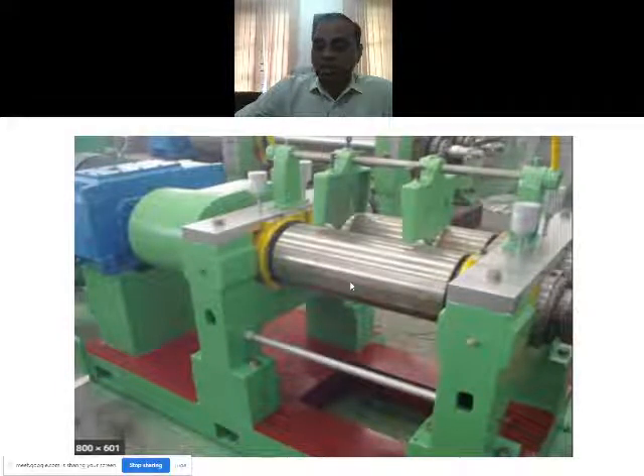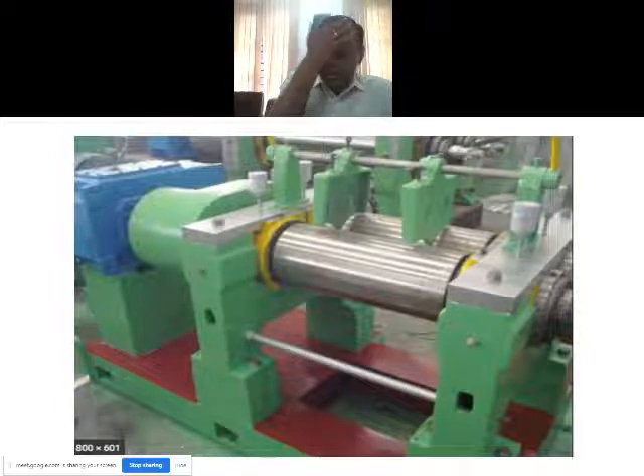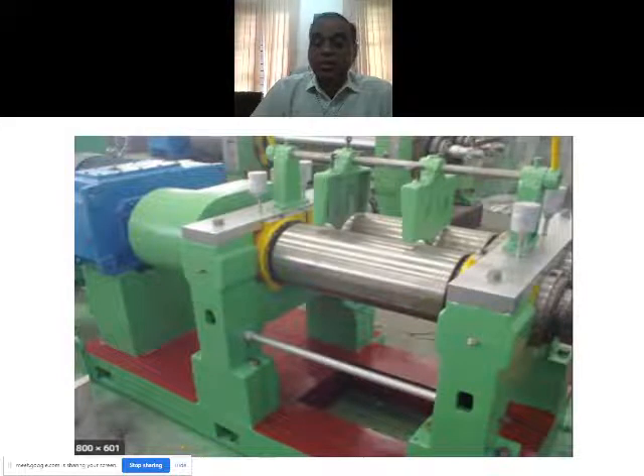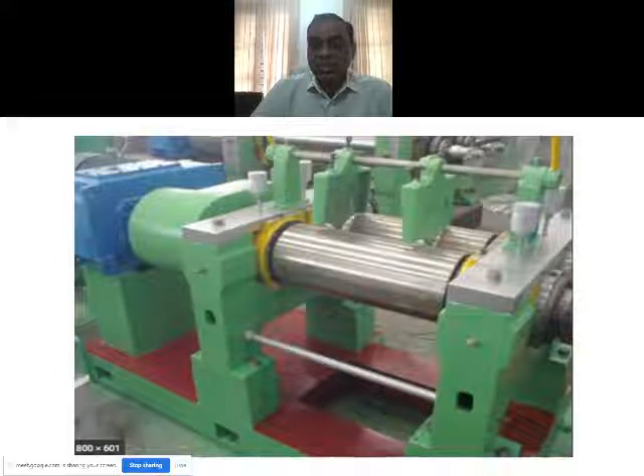Then the temperature is maintained. If you have more temperature, there are multiple problems. One is the viscosity will be down, because of which the mixing efficiency will go down. Another is thermal degradation will be more. Another is the band will stick to the roll, and then the processing will be difficult. And there can be a stage called bagging in between, I mean the material detaches from the roll surface, and then you cannot process it. As the temperature further increases, then you are in trouble, then it will stick, and the whole thing cannot be processed.